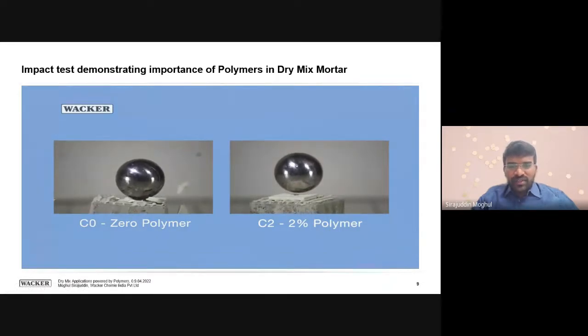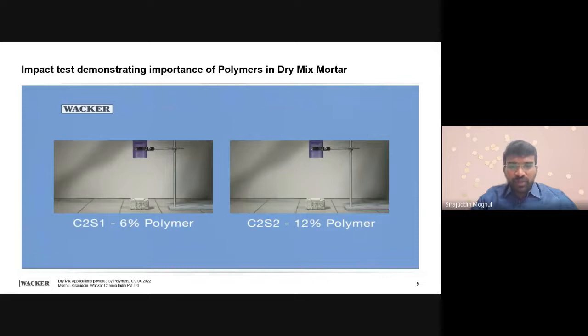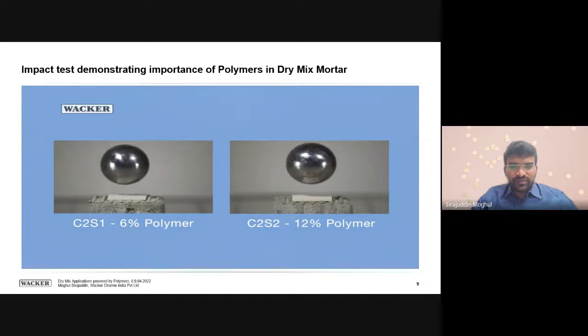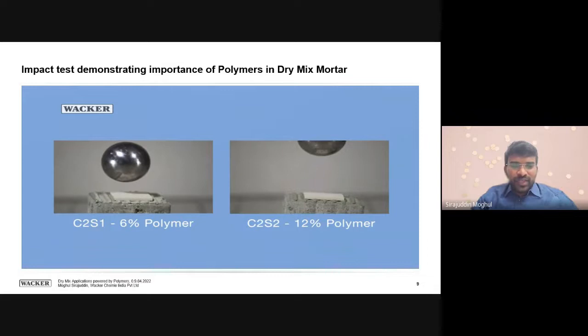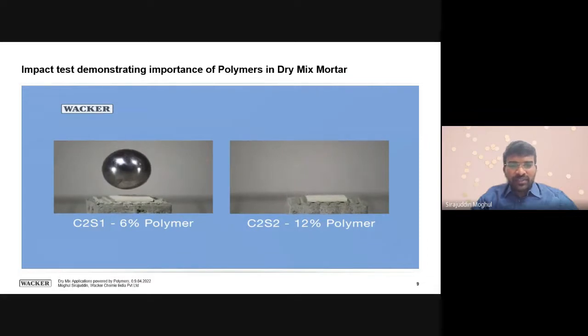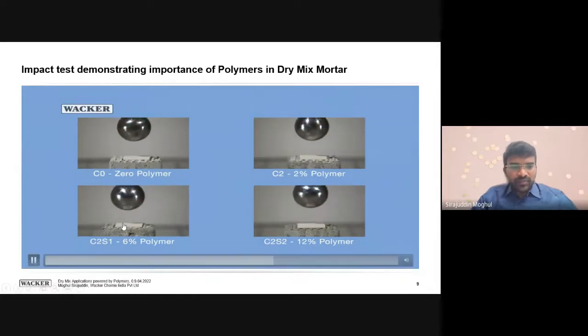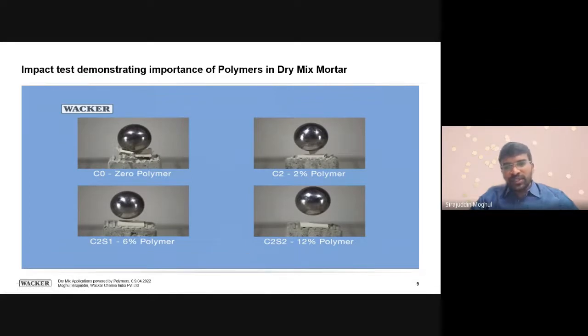And now you can see what happens when we add more polymer to the tile adhesive. See, it doesn't break. So as we increase the percentage of polymer in the tile adhesive, and then use that mortar, that will enhance the performance of our floors.